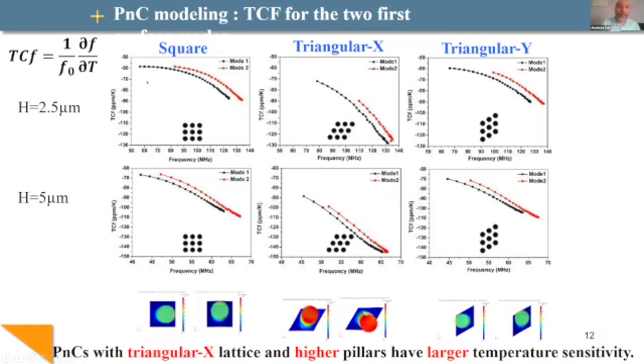we can see that when we are at, for example, 60 megahertz here, the propagation is in lithium niobate directly. But when we are near 120 megahertz, the mode is localized inside the pillar. For that reason, we don't have the same sensitivity here and there. And if we see the square phononic crystal and triangular Y, we have exactly the same sensitivity. However, if we see the triangular X phononic crystal, the sensitivity around the resonance is not the same. Even though the crystal is exactly the same, just the distribution of pillars on the surface defines the sensitivity.